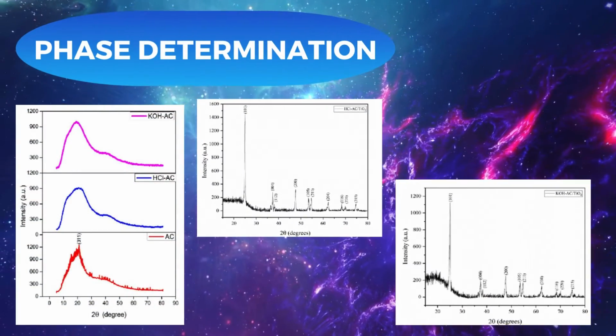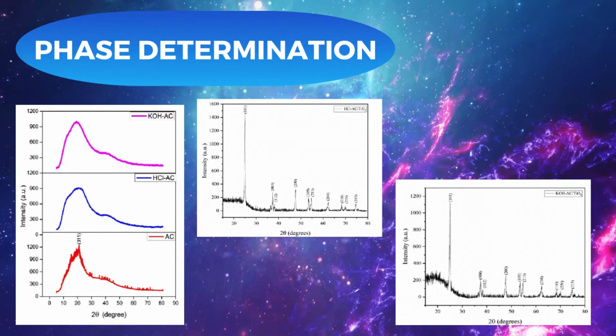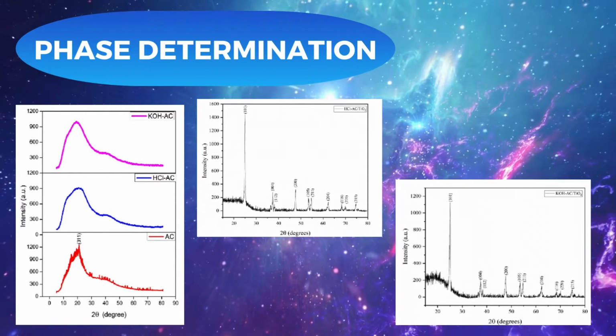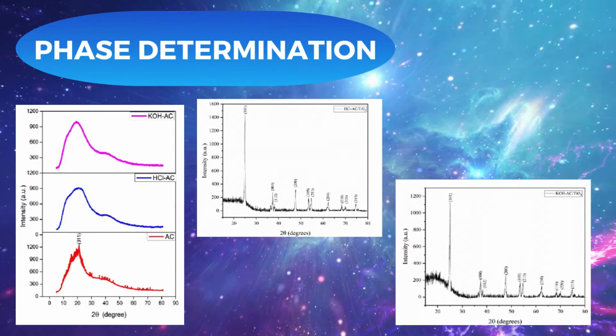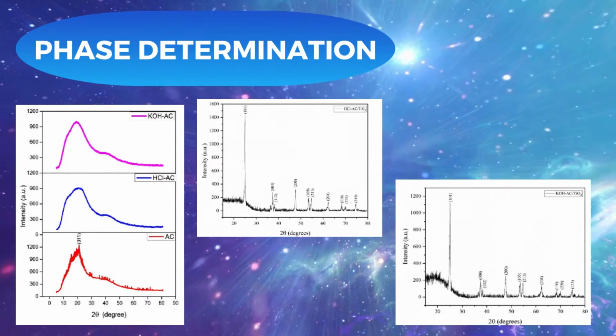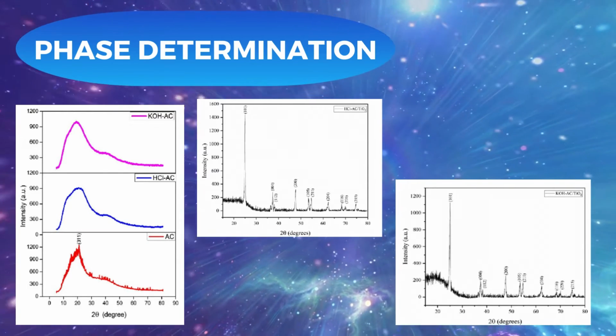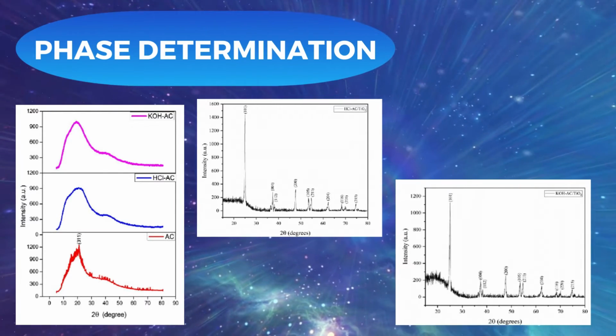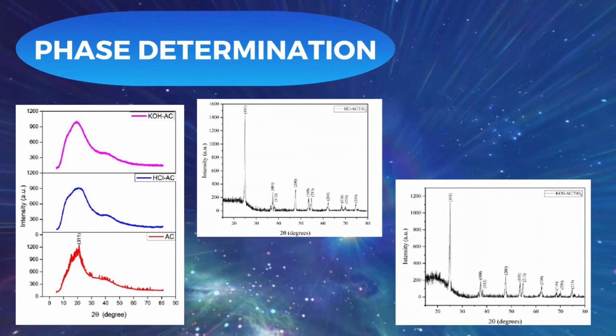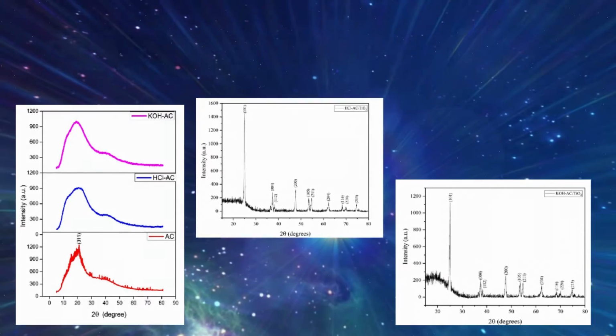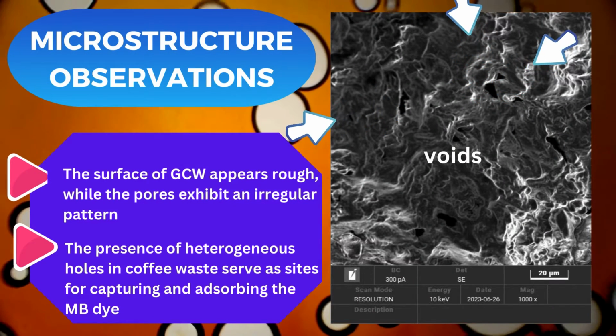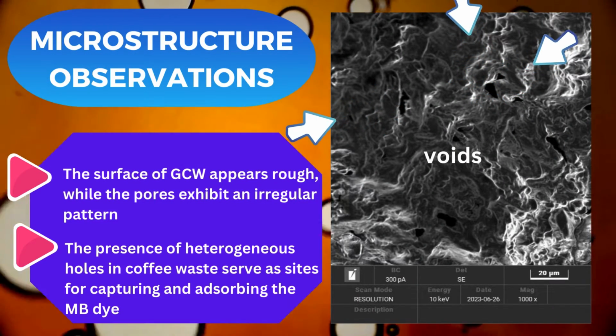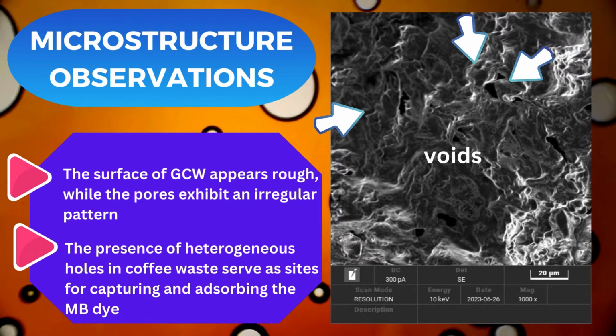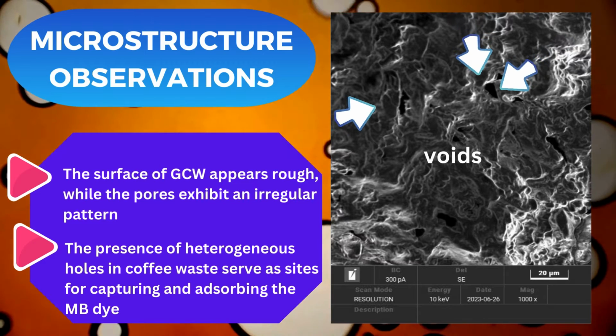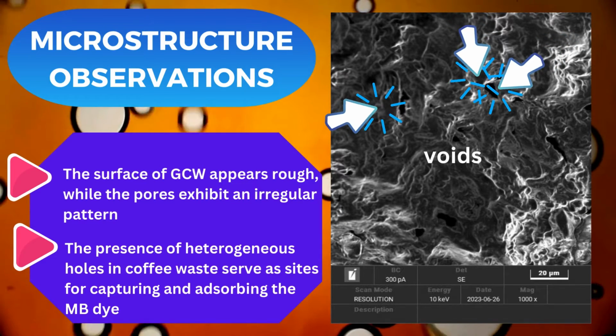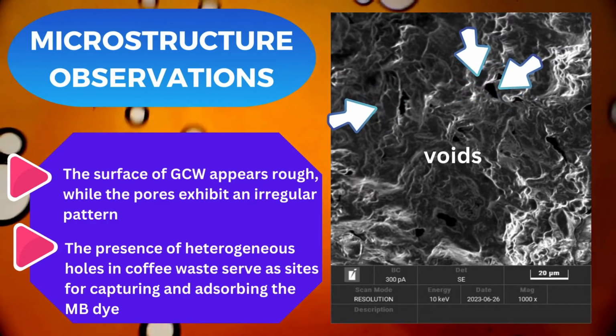Next, for the phase determination result, the XRD pattern of activated carbon reveals a semi-crystalline structure consisting of both amorphous and crystalline components. Meanwhile, the two activated carbon composites show similar diffraction patterns, with the crystallographic phase of the tetragonal structure of anatase TiO2. From microstructure observations of the raw sample, the surface of ground coffee waste appears rough, while the pores exhibit an irregular pattern. The presence of heterogeneous holes in coffee waste serves as sites for capturing and absorbing the methylene blue dye.